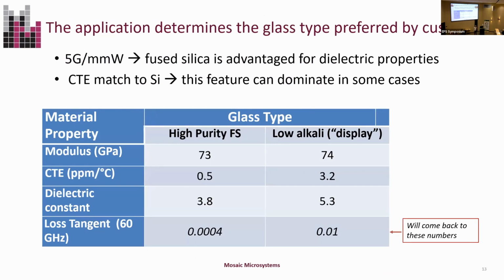So people's application determines which glass they find to be the most appealing for their application. And certainly for millimeter wave things, the very low loss of fused silica is usually very appealing. But there are some times where the fact that there's a CTE match of the more display-like glasses to silicon can actually win the day, even though it's much lossier. So the modulus of those glasses is very similar to each other. The CTE is quite different. So of course, fused silica is 0.5, where the display glass has been tuned carefully by the Cornings and Schotts of the world to be close to 3.2. So very, very matched over a range to silicon. Dielectric constant and the loss tangent are the ones that can actually distinguish for various applications here.